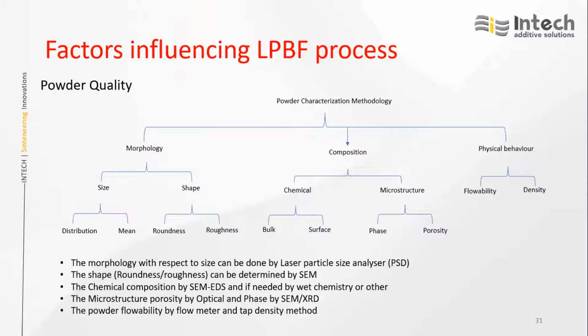Here we are spreading the powder on the powder bed, so the powder needs to be good enough to spread well onto the building platform. So flowability we need to check, and the tap density, like how good the packing of the powder is happening for a given layer. If it is loose powder and less amount occupies the build platform, then getting good density is not possible. So tap density should be maintained properly so that we get good density powder.